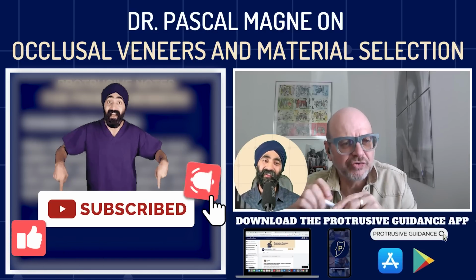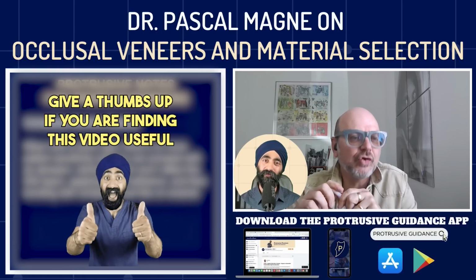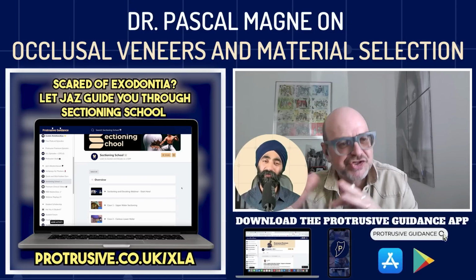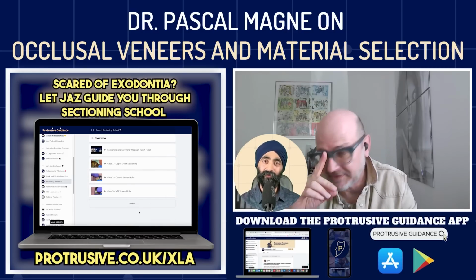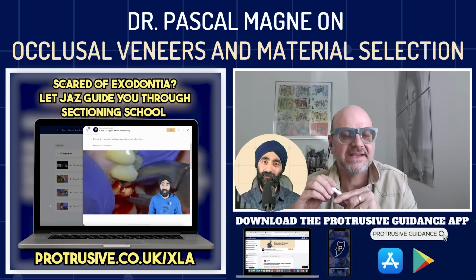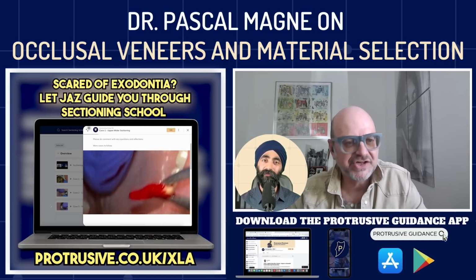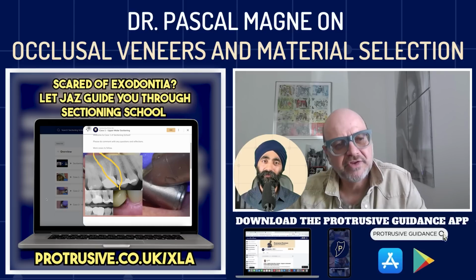Patient will not have sensitivity anymore, and you can bond your onlay as you would do if the preparation was only in enamel. That means you clean this prep by air abrasion, etch. You can etch the entire surface. Etching is not going to affect the IDS layer. And then apply fresh adhesive and your luting composite.